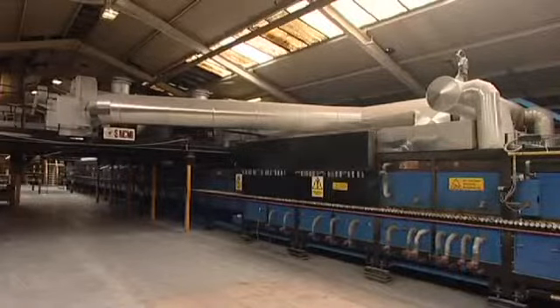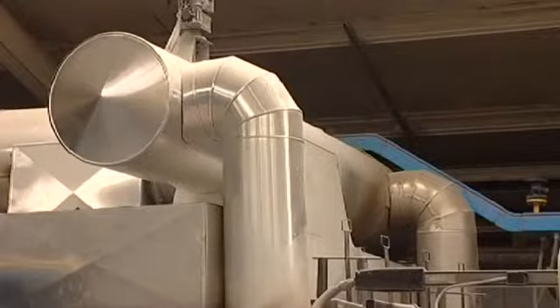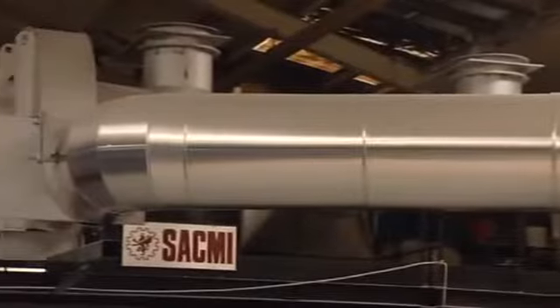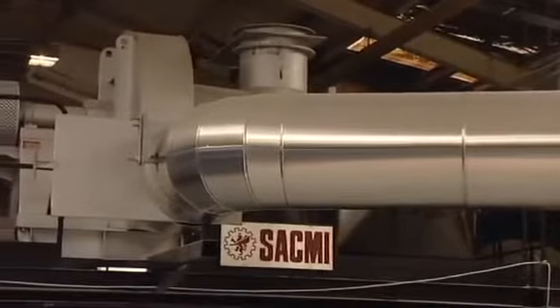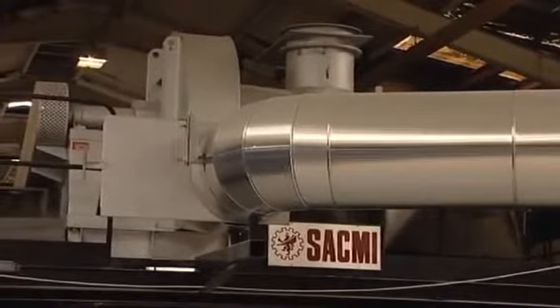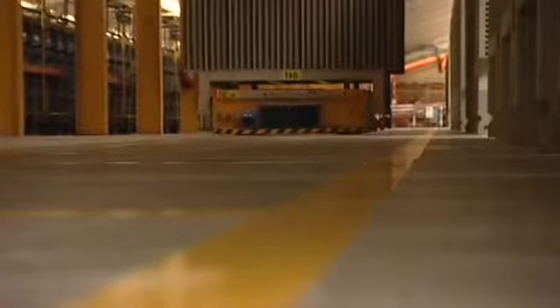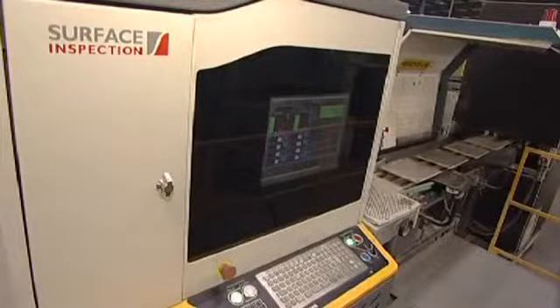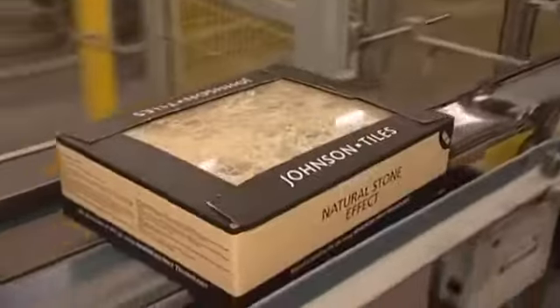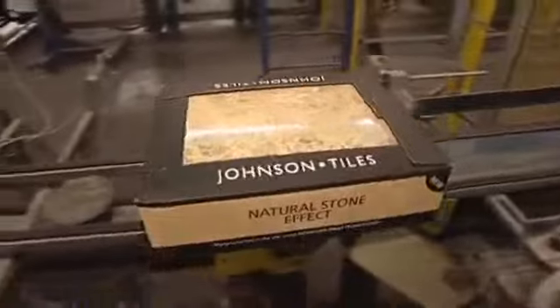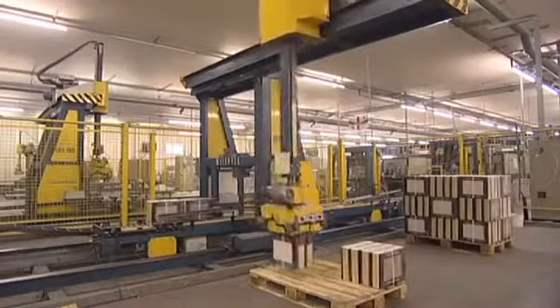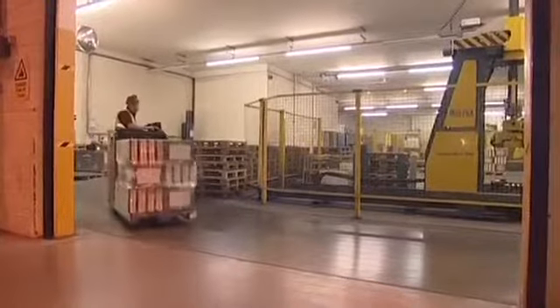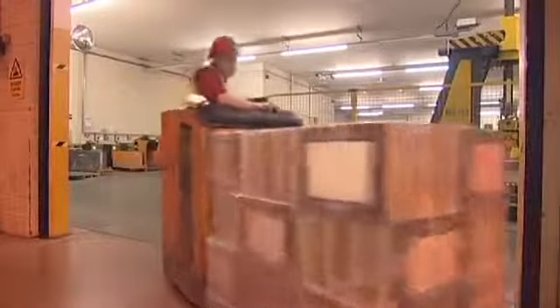The kiln uses natural gas for heating, and this company has installed a heat recovery unit on the kiln we see now to draw waste heat from the exit end of the kiln to preheat the combustion air, so reducing consumption by 10%. The cooled tiles are fed back into the roller cage to be passed to the final inspection lines and then to be packaged. After packing and loading onto a pallet, the tiles are sent to the warehouse for dispatch to the customer.